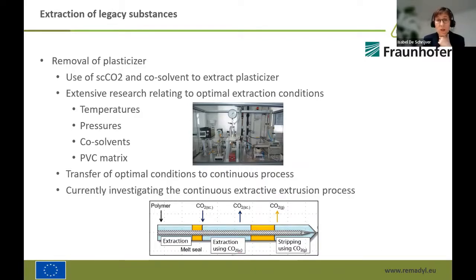First of all, we did some trials on lab scale, where we played with the optimal extraction conditions, which would mean temperature, pressure, combination of the co-solvents, and of course also having a look at the impact on the PVC matrix. Now we are transferring those optimal conditions to a continuous process, which you see here in the picture below. So we will use a continuous extrusion line where the supercritical CO2 is being added to the polymer melt together with the co-solvent, and where we are trying to do the removal of those plasticizers, the extraction in line during the extrusion of the PVC materials.